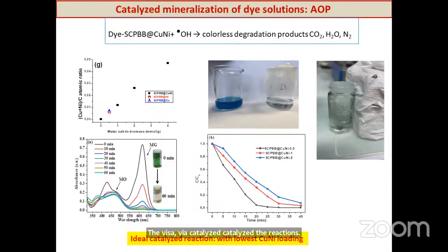So this work is now under revision for publication in Environmental Research, but you can see we try to control the kinetics of the degradation reaction. We expected probably more activity with 4 times loading of copper nickel, but actually we found that the lowest loading of nickel here provides the fastest degradation of the dyes, and this is because at high loading the nanocatalyst is agglomerated and the activity is reduced because we have less access to the catalytic sites.